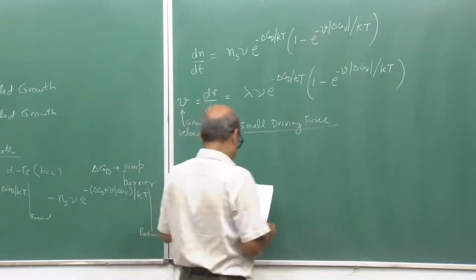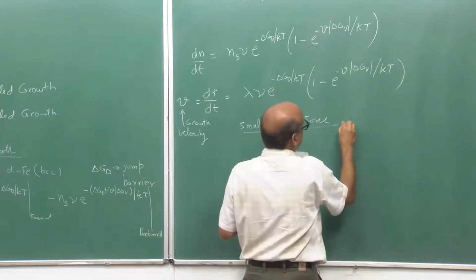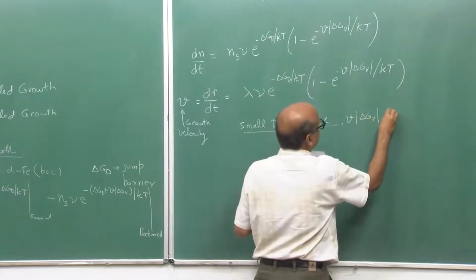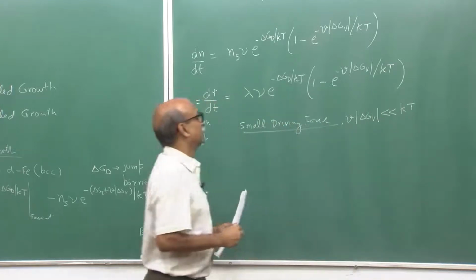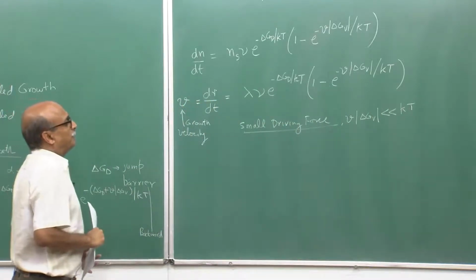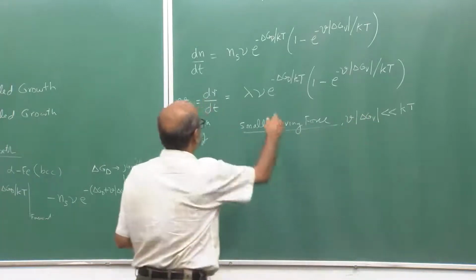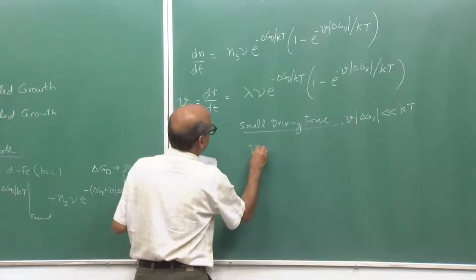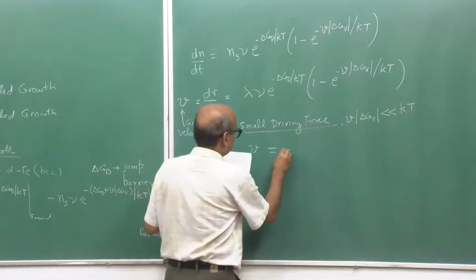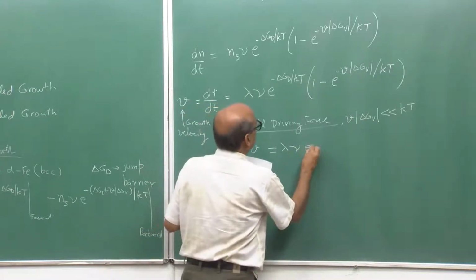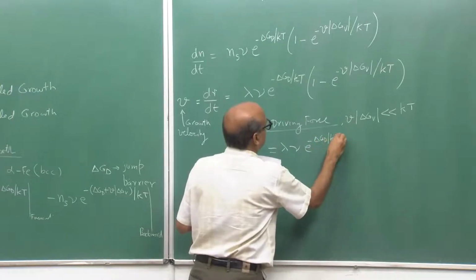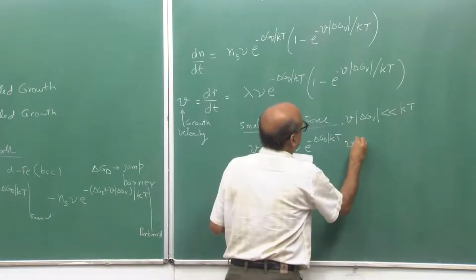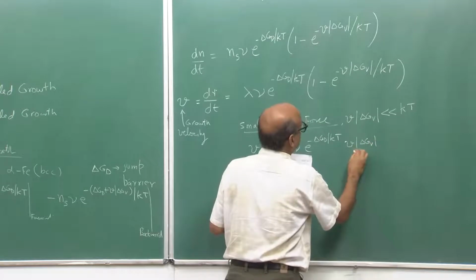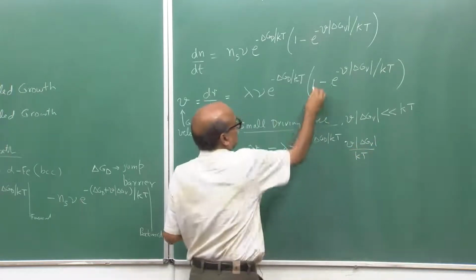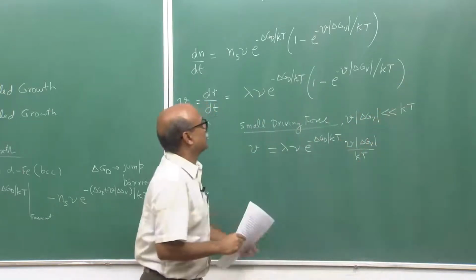Small driving force means that the term V delta GV is much smaller than KT. If we had a very small driving force, then I can simplify this and write the growth velocity as simply lambda nu e to the power minus delta GD divided by KT times V delta GV upon KT. That is, the term in the brackets can be approximated by V delta GV upon KT.